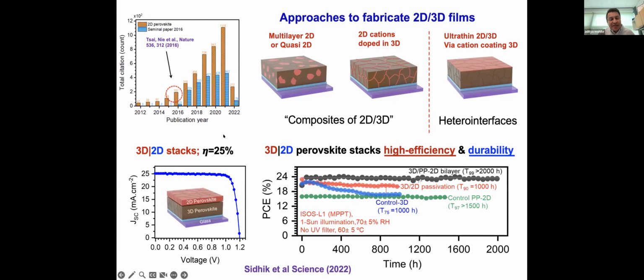So we recently, and I won't speak about this, but we recently had this really nice paper on taking the 3D perovskites and deterministically putting down whatever 2D layer that we wanted on top in such a way that we can actually get a really nice band alignment from the 3D to the 2D layers, where they're actually working like charge transport layers. And so when you do that, you can get pretty nice devices, 24, 25%.